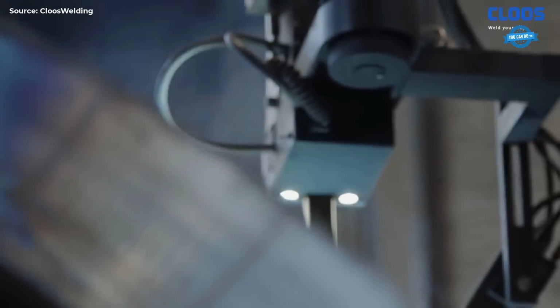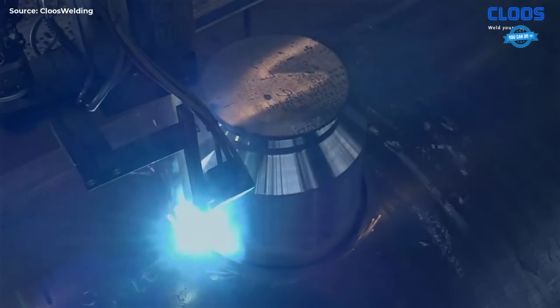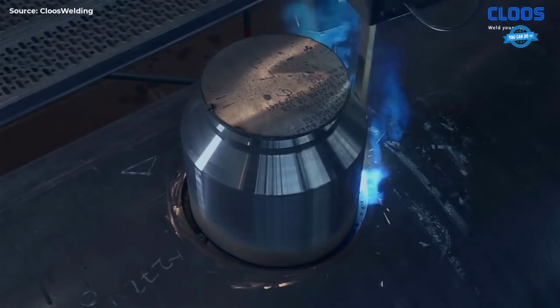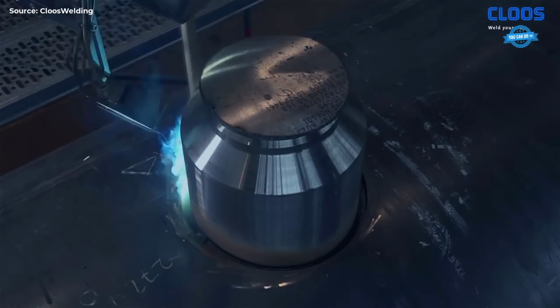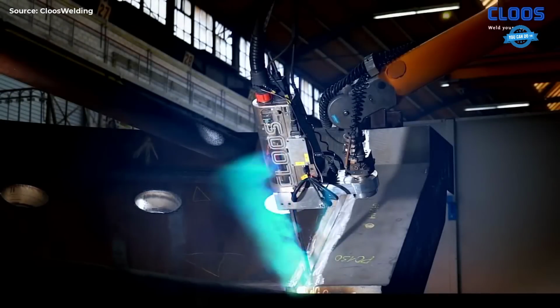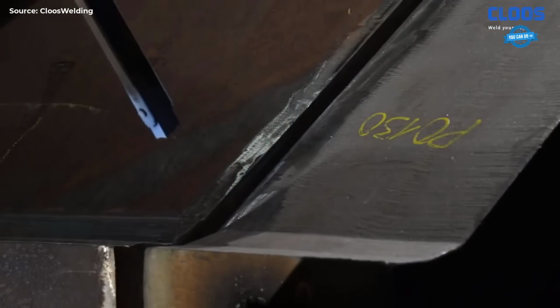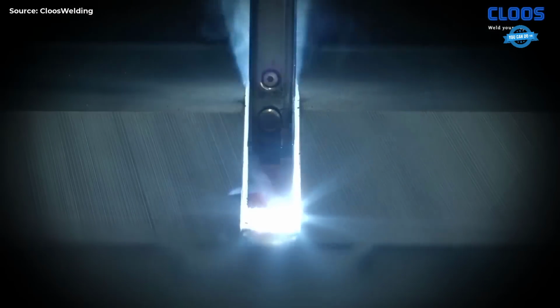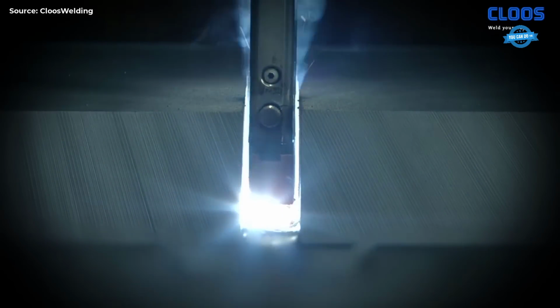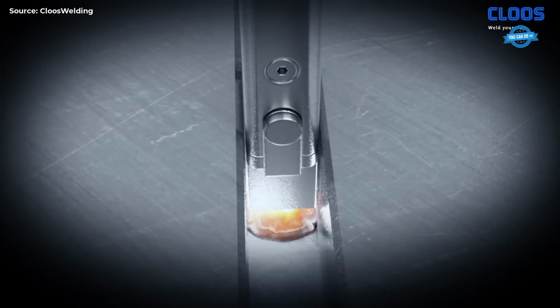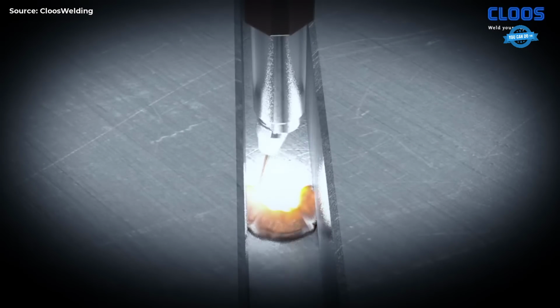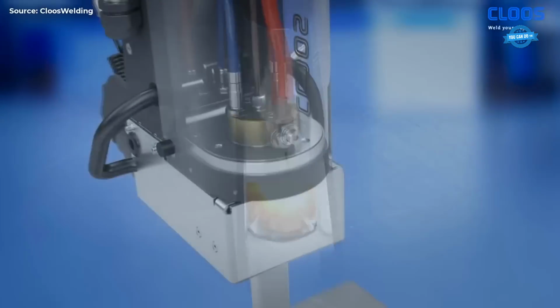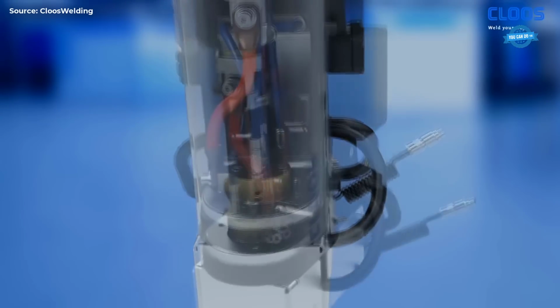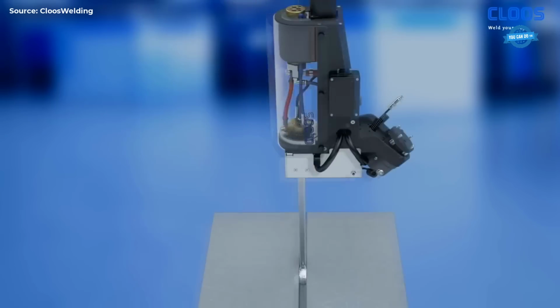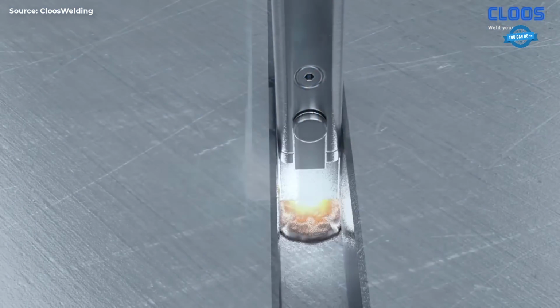The CLOOS MIG narrow gap technology offers a particular economic efficiency for welding thick-walled component parts. In comparison to the conventional weld seam preparation, the weld seam volume can be reduced by about 60%. The rectangular narrow gap blade, with a length of up to 400 millimeters, guides the wire electrode, the shielding gas, and the cooling water. The weld seams with the typical constant seam structure meet the highest quality demands.